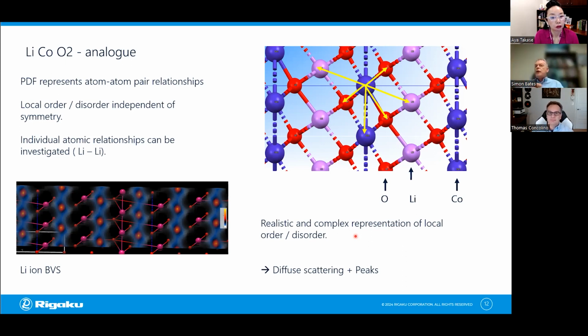But one of the issues, particularly with NMC, which is one of its main failure mechanisms, is that as all the lithium leaves, you've got an empty channel. There's nothing there. I think it was Aristotle who said, nature abhors a vacuum. So if you empty the channel, something bad is going to happen, clearly. What normally happens is they collapse. And when they collapse, you can't get the lithium back up through them again because there's no channel there.